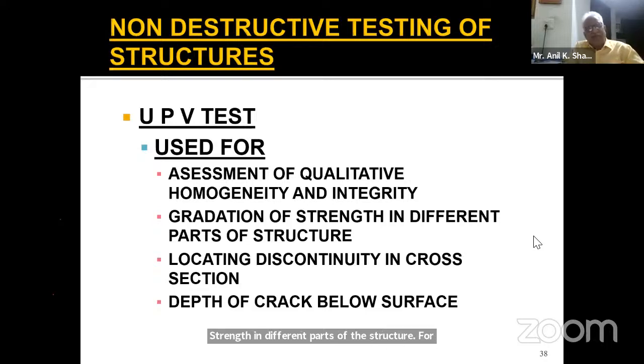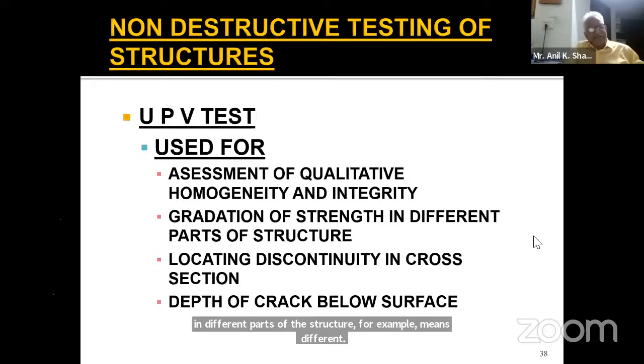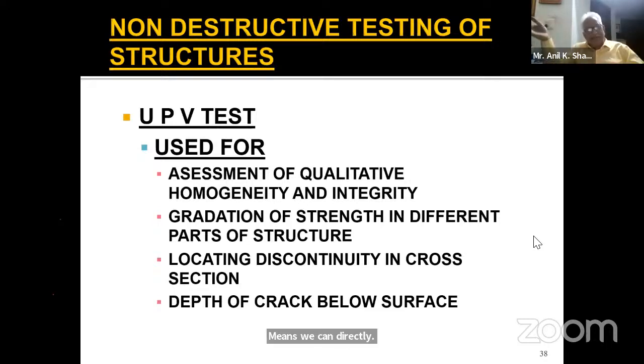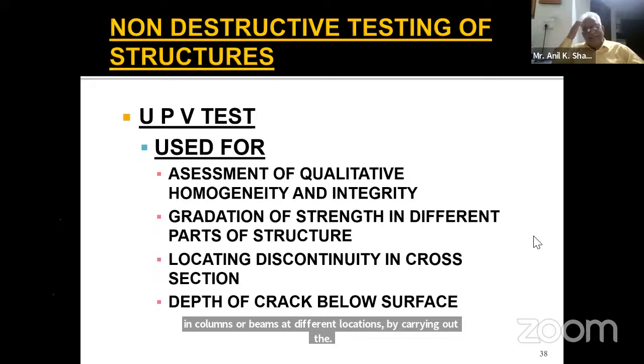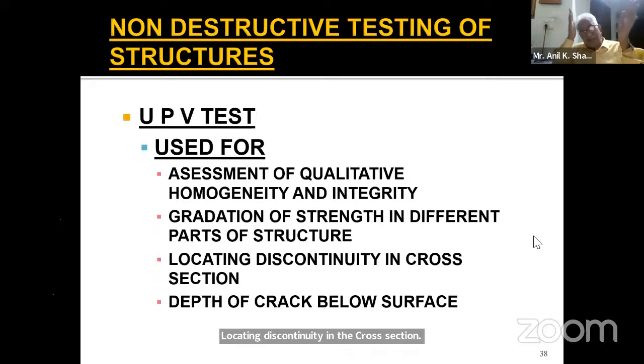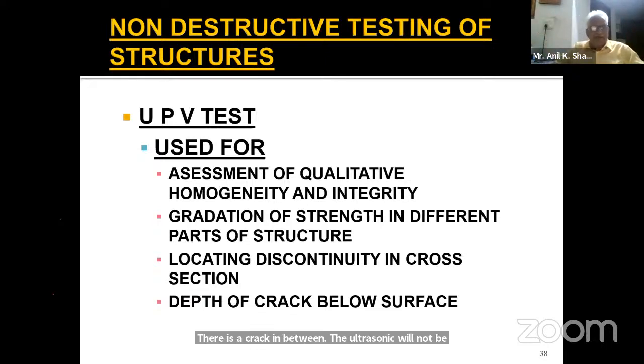For example, we can directly differentiate the quality of concrete between different beams or columns at different locations by carrying out the ultrasonic pulse velocity test, the UPV test. It also locates discontinuity in the cross section. If there is a crack in between, the ultrasonic pulse will not be able to travel directly, so it gives an understanding of the discontinuity in the cross section of an RCC element. Depth of a crack below the surface can be determined using the UPV method with a normal trigonometric formula.